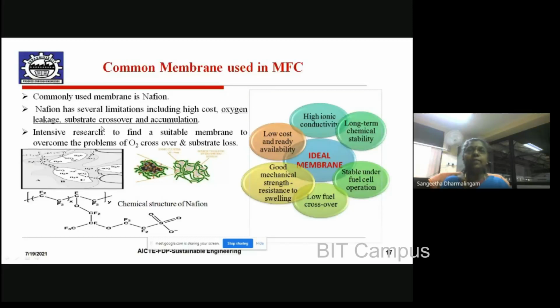So what happens is Nafion is permeating, or allowing, the oxygen to diffuse through it and reach the anode. So when this oxygen crosses over from the cathode to the anode, the anaerobic condition required for the microorganisms to grow and do their functioning is going to be bothered, it's going to be damaged. So this oxygen crossover is a great problem with respect to Nafion, and therefore a lot of other membranes which do not allow the oxygen or the substrates to cross over are gaining more importance in the research angle.